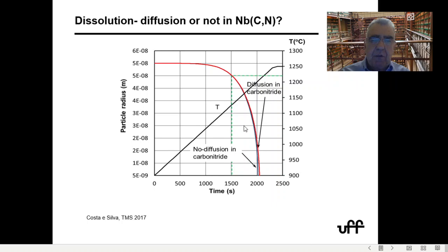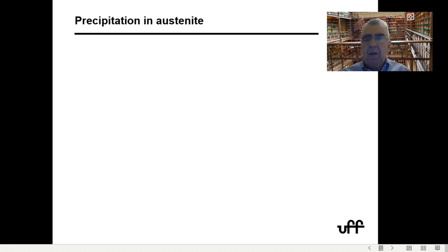Interesting enough, there was a question some years ago whether there was diffusion in the carbonitride or not. Physically, you would believe that there's no diffusion inside the carbonitride. But they did the calculations assuming both, and the controlling step was not the diffusion in the carbonitride. So essentially what we found was that it is not relevant whether the diffusion is happening in the carbonitride or not.